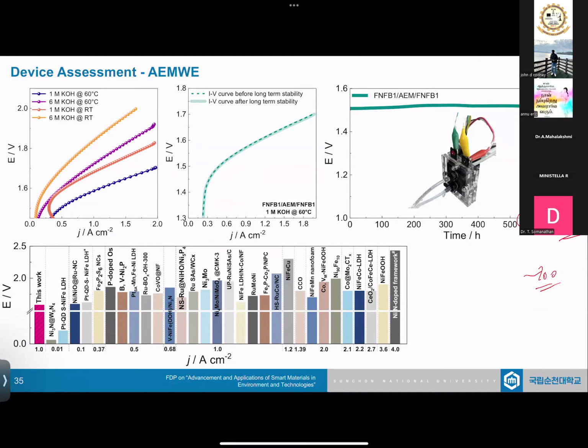You have to move further, because if you are doing research with respect to industrial application, you want your material to be pushed further for industrial application. Do they work in industry at 10 milliamps or 100 milliamps? No. They have high current densities, 1 ampere, 1.5 ampere, 2 ampere. At least go up the ladder, go to that level. And doing just 12 hours or 24 hours in your device or in your overall water splitting is not that great. You have to push much further, to a week.